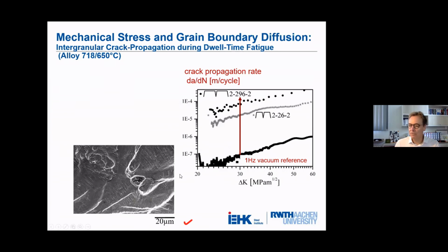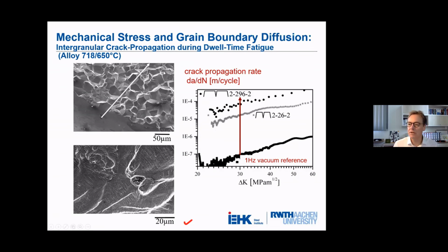While under vacuum conditions or without dwell time, we have only cycle-dependent crack propagation, as is shown here with the typical fatigue striations. Once we increase to dwell times, then we have an increase in the crack propagation rate by 2 orders of magnitude, which means 100 times faster crack propagation, and the fracture surface looks completely different. Here we see the non-deformed grain boundary facets. That is the influence of the dwell times.